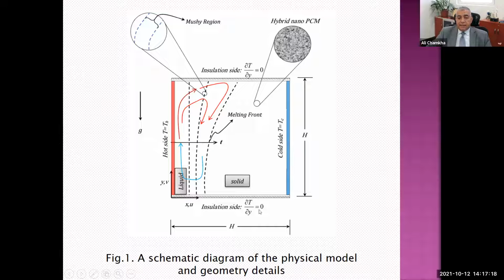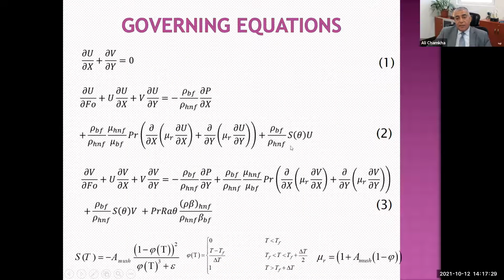And this is the diagram. This region where you have mixed solid and liquid is the mushy region. You have to model it differently. If you look at the model, this is the model. This is the viscosity of the hybrid nanofluid. This is the viscosity of the base fluid. What's different here is that S is the Kozeny-Carman model that expresses the effect of damping in the mushy region.